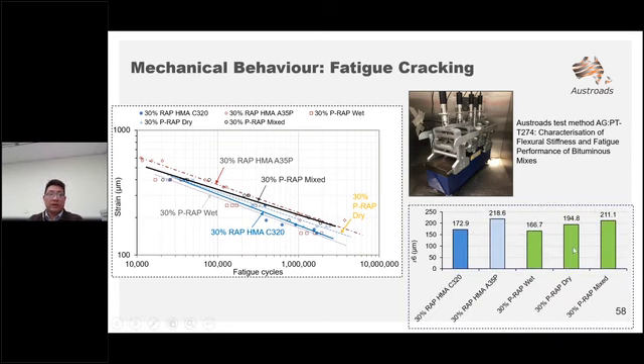As we can see here, the 30% PRAP dry and 30% PRAP wet show higher epsilon 6 values than the 30% of RAP from conventional RAP, by about 13 to 20%. Among the mixes, 30% RAP from A35P demonstrates the best fatigue performance compared to the other mixes. And also, we got the 30% PRAP wet has a slightly lower epsilon 6 than the conventional 30% RAP from hot mix C320.